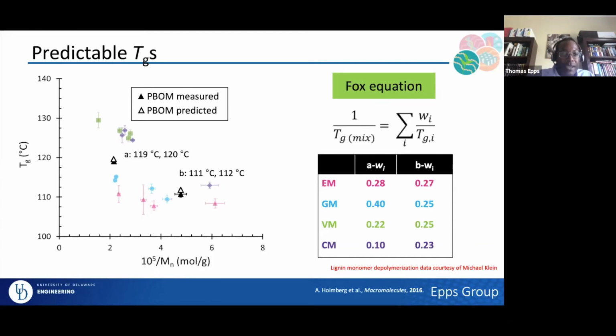So we're able to do that, and if you look at the left-hand side, what you can see is the open triangles, and this is just two of many examples, where you have the predicted glass transition temperature data. Then what we were able to do, in collaboration with Dion Vlachos's group, is actually do the pyrolysis, clean up, make the block or make the homopolymer in this particular case, measure the glass transition temperatures at the two pyrolysis conditions, and actually we're able to get the solid data.